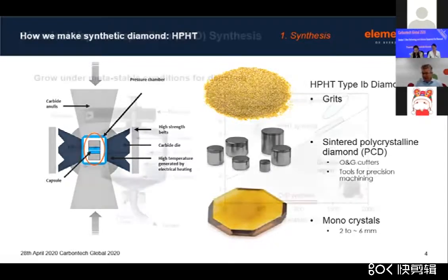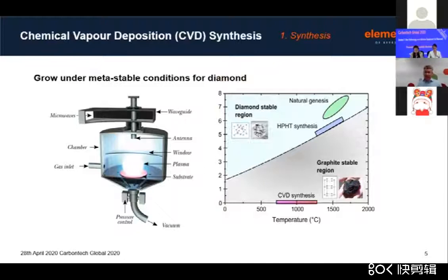And obviously research began in the early, well, really in the 1980s, into what's known as chemical vapor deposition, where effectively you don't work in the actual right area of the phase diagram, but you're actually taking the surface properties and using atomic hydrogen, you're able to actually grow diamond in the metastable region. And a lot of the work is really focused around actually how you deliver that plasma that disassociates the hydrogen and generates the right growth environment for you, and delivering in microwaves, which turned out to be one of the best ways of making that into that resonance chamber, creating the high purity conditions in there and the substrate and growing the diamond on there.